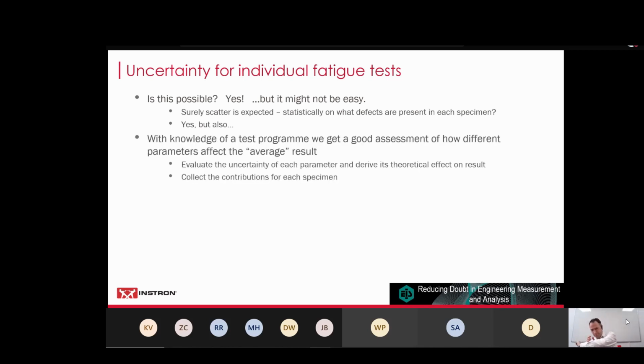True, but also, once we've done a test program, or some past ones, we've got a good assessment of how different parameters affect the average result. So temperature versus fatigue life, strain amplitude versus fatigue life. So for each of our parameters, let's say the strain amplitude, we can evaluate an uncertainty. And because we know about the test program as a whole, we can derive that theoretical contribution to the result uncertainty. And we can collect those together.